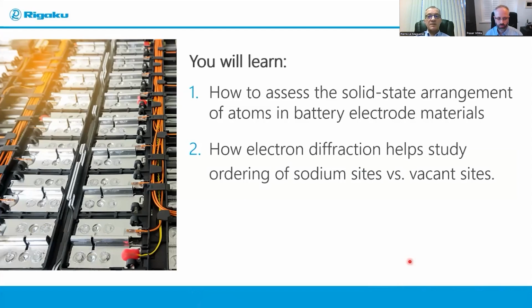Indeed, during charge and discharge of batteries, sodium ion cathodes undergo crystal structure changes because precisely the sodium ions are being added and removed from the battery material. And the way the crystal structures change directly influences the efficiency of the battery and its long-term stability. So the question is therefore whether one can locate the sodium ions in some of these crystal structures, or even more, whether the ordering between vacant sites and sites occupied by sodium can be assessed.